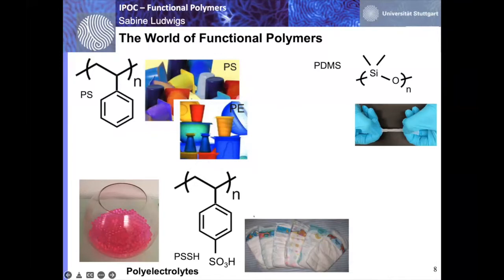And one example is this polystyrene sulfonic acid. So here you see the sulfonic acid. This is the class of polyelectrolytes. If you use polyacrylic acid, which is another polymer from this class, you can, for example, make these baby pampers, or also these pretty pearls, which you can buy and which swell up in contact with water. By the way, the sulfonic acid bearing polymers are also in these polyelectrolyte membranes, which are used for fuel cells and which were mentioned as well in the talk before.